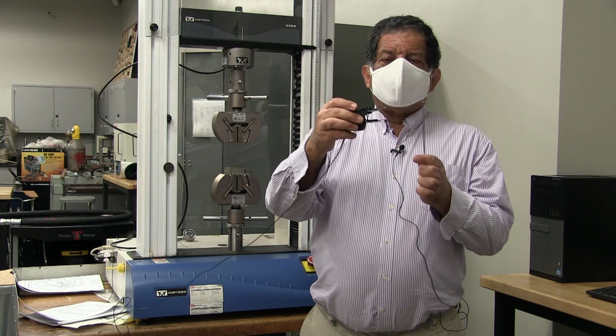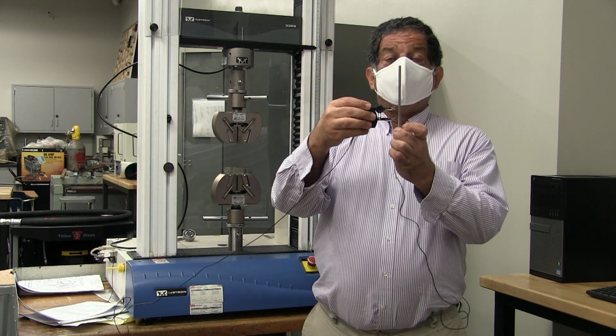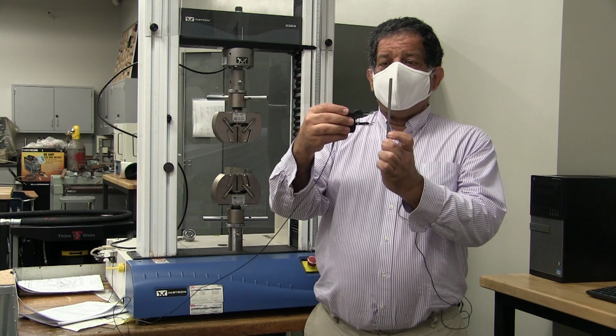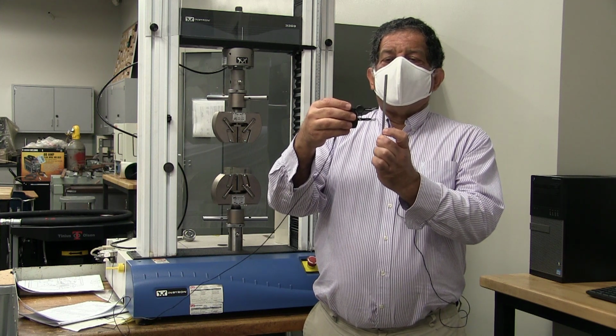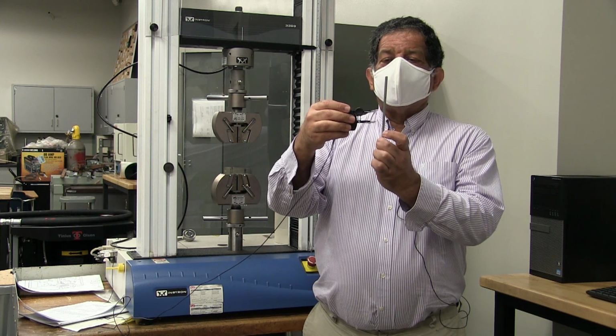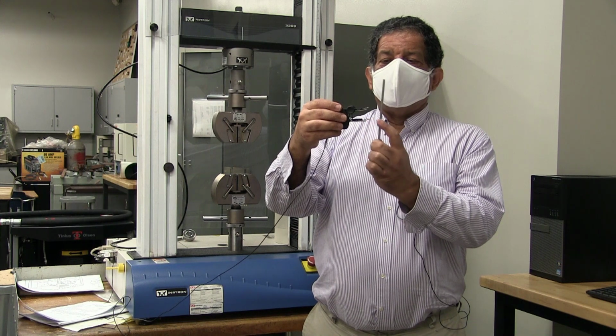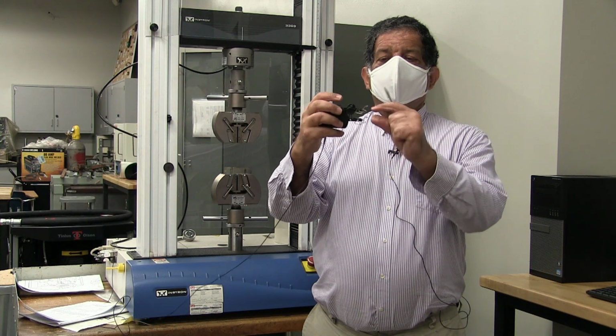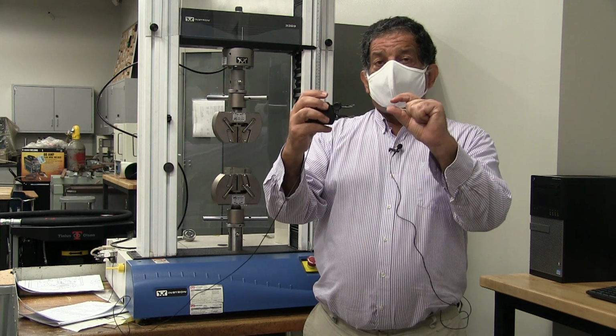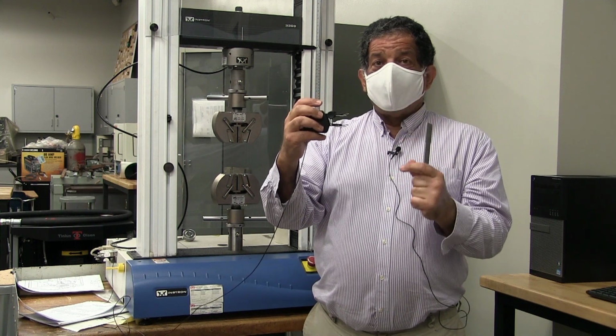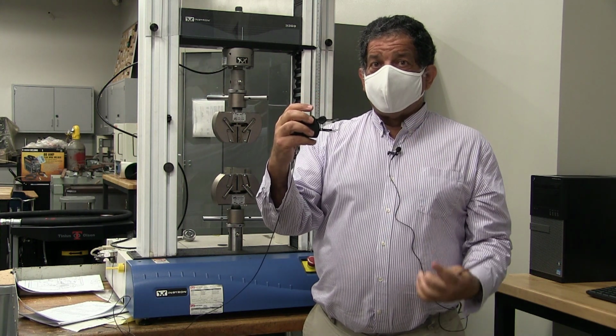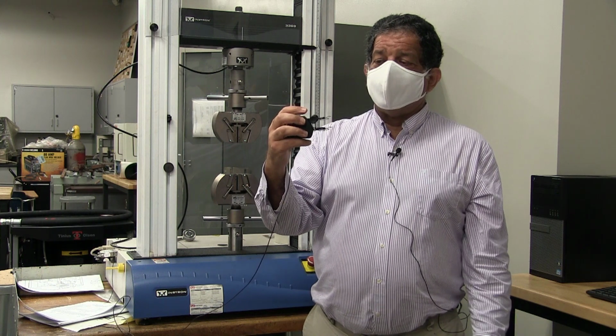So I'm going to mount this extensometer onto the center of my specimen after I have it in the machine. We're going to measure the displacement of the specimen over a 1-inch gauge length for just 1% of the deformation, and that will allow you to do your calculations of the modulus and the yield strength.